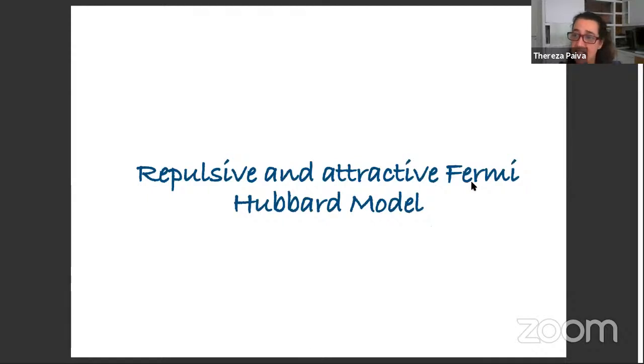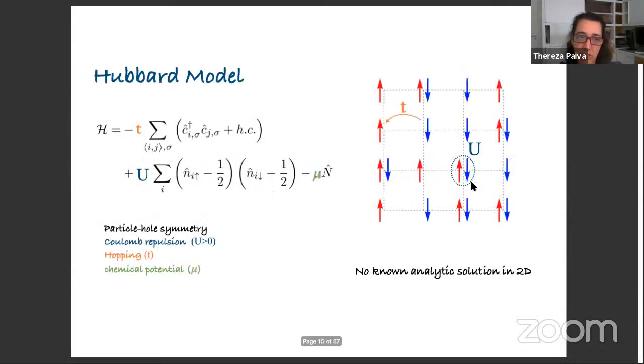So the most studied one is the repulsive Fermi Hubbard model, and I'll start with it. So in this easy looking but not easily treatable Hamiltonian, we have these three terms. A hopping term, where we can have electrons going from one site to the neighboring site, and I am only considering nearest neighbor hopping. And we do have repulsive interactions in this case, where whenever two fermions meet in a single site, they experience repulsion U. And I have written this term in a particle-hole symmetric form, and I will come to it in a bit, why this is important. And also we have a chemical potential here that regulates the amount of particles we have in the system. So if we want more or less particles, we change the chemical potential.